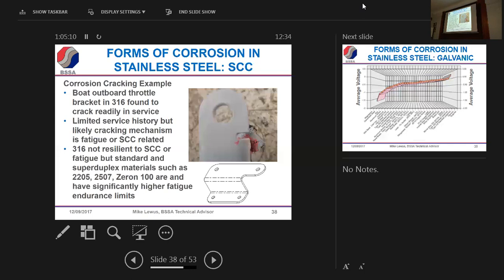And it is cracking, that was indisputable, so it's very likely that just that roughness has had an impact on prevalence of cracking. Easy one to solve potentially. Just dress the edges, clean them up, or switch to something like duplex, which has got a higher fatigue endurance limit.